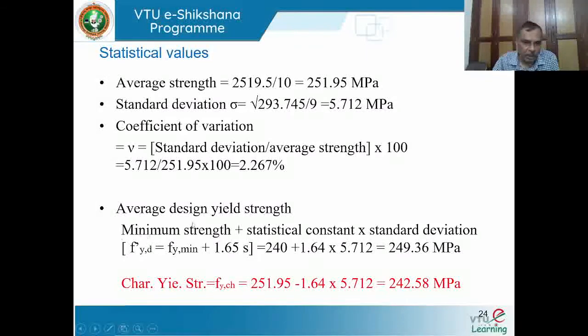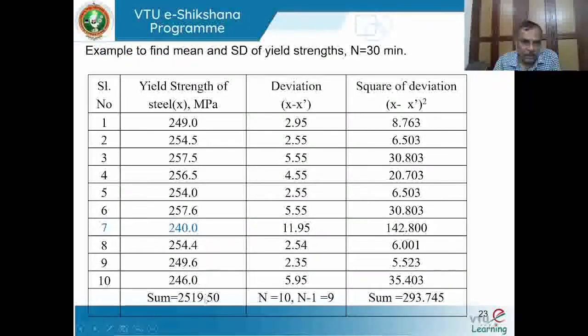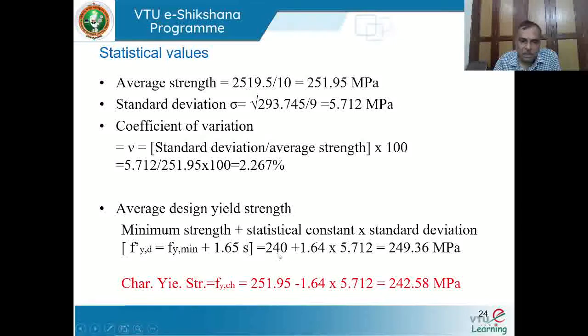So with this, you can calculate the average design yield strength. The average design yield strength is just for our requirement we are calculating, but that is not the value we use in the limit state method. Just to have some information, the average yield strength is nothing but the minimum strength amongst the 30 samples. Kindly see here, in 10 samples, the minimum is 240, and that 240 plus the value 1.64, the statistical value for 5% probability, and 5.712, the value which you have calculated as the standard deviation here, with this it is 249. So 249 megapascal is the average design strength based on 30 samples, but I have presented only 10 results.